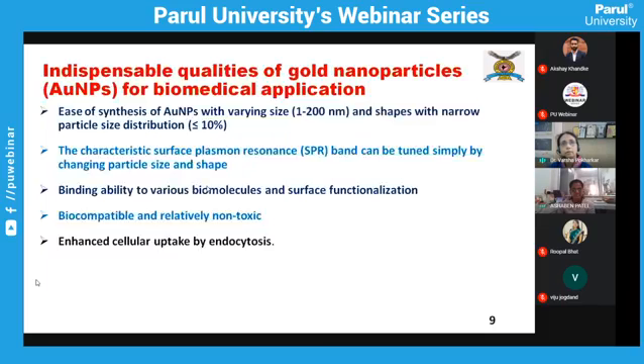So why gold nanoparticles? Gold nanoparticles essentially have very good, indispensable qualities which make them useful for biomedical applications. The first is the ease of synthesis of gold nanoparticles with varying size range, right from 1 nanometer to 200 nanometer, and varying shape, with a very narrow particle size distribution.